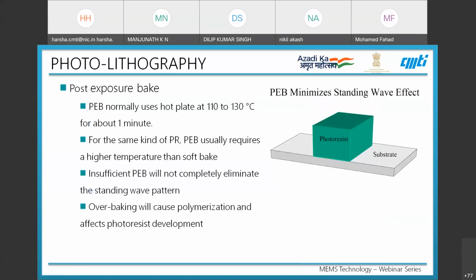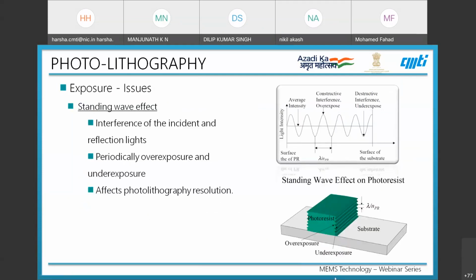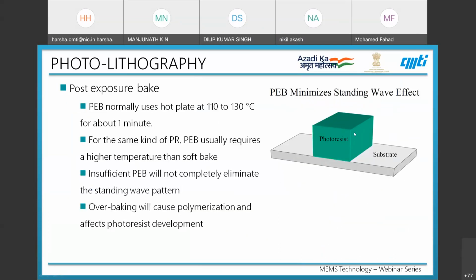This effect has to be eliminated. The best methodology to eliminate the standing wave effect is to introduce a post-exposure bake after the exposure. As shown in the previous slide, the image had overexposure and underexposure wave patterns, which can be eliminated by the post-exposure bake, as shown in this image.